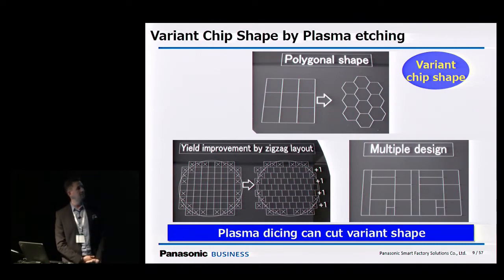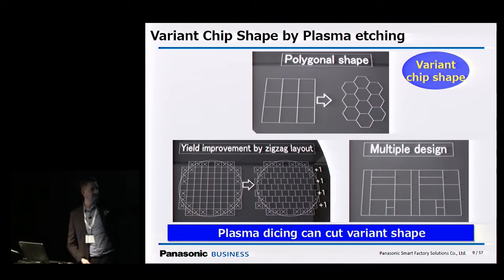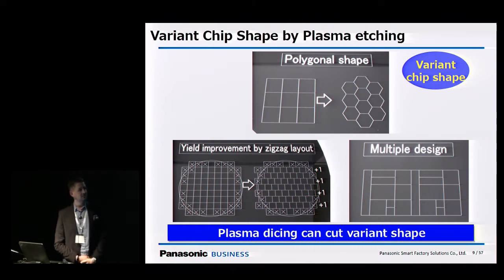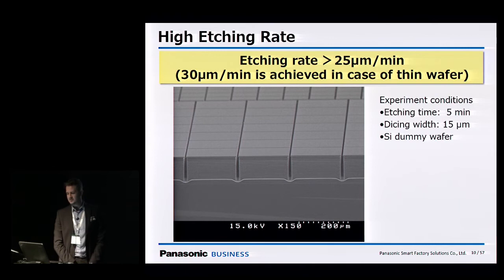And because it's a mask-based process, you're no longer limited by a standard grid shape, so you can start to think about variant shapes or offsets if the devices are relatively large, and you can also include multiple sizes on the same wafer. Anything is possible, basically. For the basic case of silicon, etching speed is around 25 micrometers per minute. And if the wafer is exceptionally thin, the initial dicing speed can be up to 30 micrometers per minute.